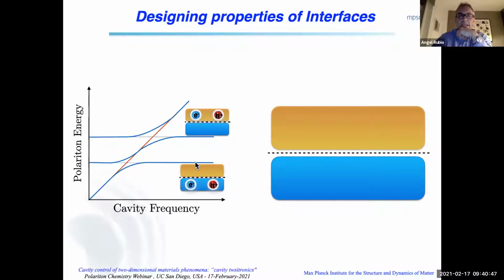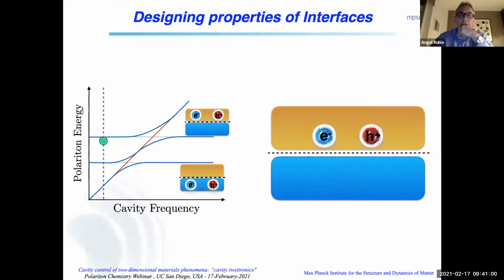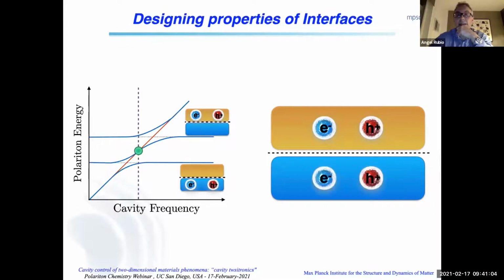Let me give you the cartoon. These are two materials. What you have is the exciton of the lower one. Then the exciton is localized on the bottom 2D material, then on the upper one, and they have different energies. But when the cavity gets in resonance to the middle part, with this splitting of the two polaritons, then you get the exciton being excited automatically on both materials. And then, of course, you can move it to the right and exchange it.